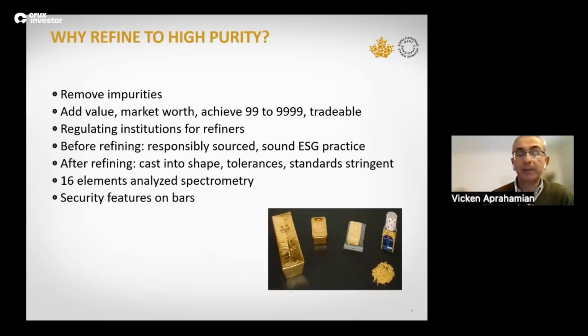So toll refiners, before refining, some of the activities that take place: they have to make sure that the gold has been responsibly sourced, that there is sound ESG practice from the source. And then upon refining, the material has achieved purity and it is cast into a shape. And there are strict tolerances, very, very stringent. Up to 16 elements are analyzed by spectrometry in the case of 4.9s.